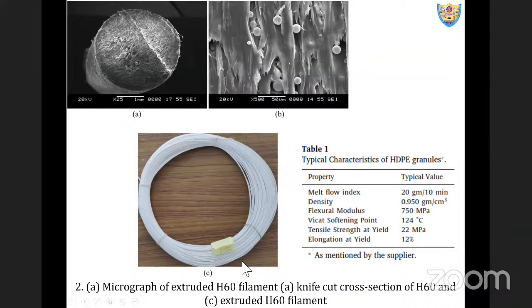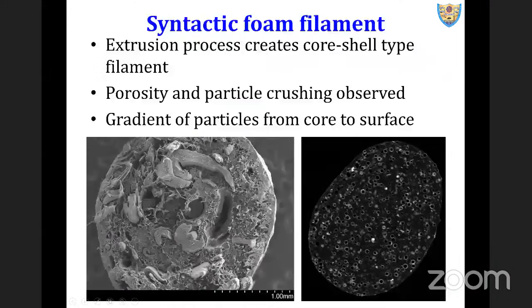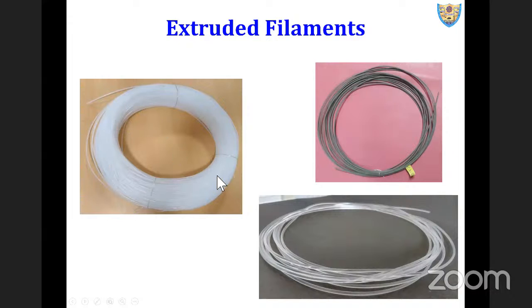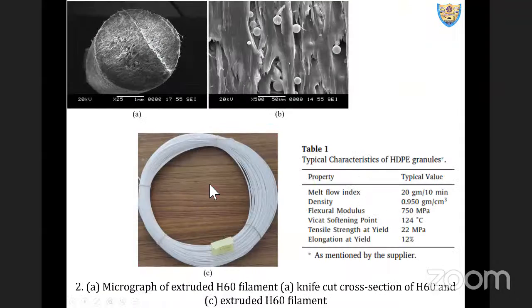So what we did, we have H20, H40, and H60 bundles of filaments, which will be acting as a core. And then we have pure HDP filament, which acts as a skin for the sandwiches. So we feed HDP filament in one nozzle, and we feed the foam filaments in the second nozzle. We exploited the second nozzle, which is supposed to be used for support material, for the core to print a multi-material system. As the 3D printer has two nozzles, we can say primary N1, N for nozzle, and secondary N2. N1 and N2 are fed with HDP and foam filaments, as I mentioned. Both nozzles are utilized while printing the sandwich.